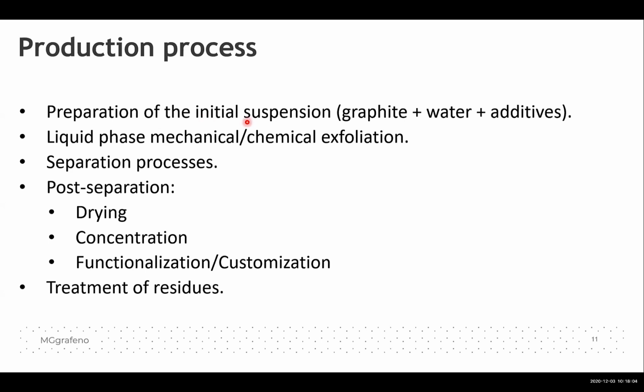Okay, so the production process, I won't talk very much about this, but we have the preparation of initial suspension, so graphite, water, plus additives. So we have the typical chemical, mechanical assisted exfoliation. We have separation processes, so we put a lot of effort here in the separation process. We really developed very, very good separation process for the material that is generated here that we call conversion. And then the post-separation. So we also developed drying, concentration, which is very interesting.